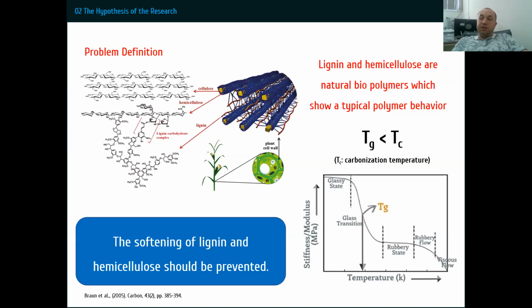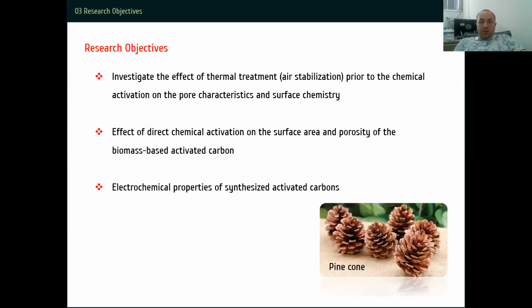A novel approach, air stabilization technique, or we can call it thermostabilization, may fix this problem. Reactions occurring during the thermostabilization increase the Tg. As the temperature increases at slow heating rate, the Tg can increase faster than the temperature, maintaining the material in the glassy state, non-tacky or non-waxy. At higher heating rates, the thermostabilization reactions are not able to maintain the increasing of Tg, and the material softens, entering the tacky liquid rubbery state, fusing together. Here are our research objectives.